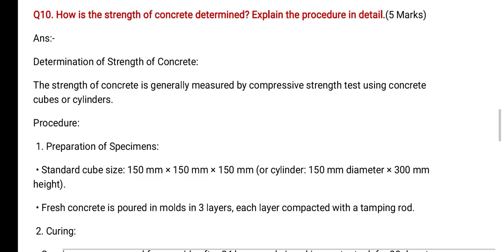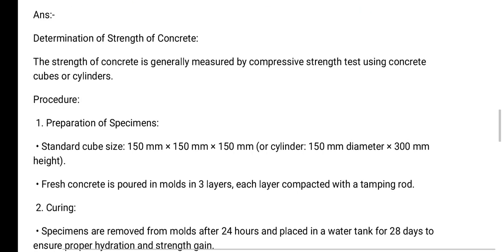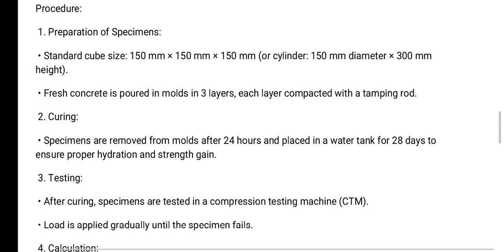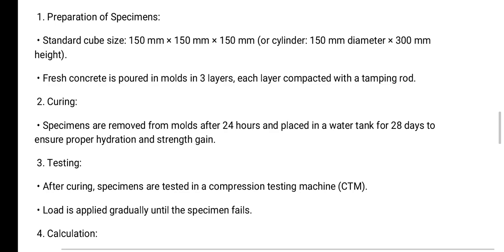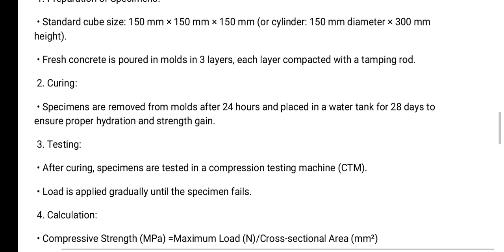Standard cube size 150 mm by 150 mm by 150 mm or cylinder of 150 mm diameter and 300 mm height is considered. Fresh concrete is poured in molds in 3 layers, each layer compacted with a tamping rod. Number 2. Curing. Specimens are removed from the molds after 24 hours and placed in a water tank for 28 days to ensure proper hydration and strength gain. Number 3. Testing. After curing, specimens are tested in a compression testing machine. Load is applied gradually until the specimen fails.